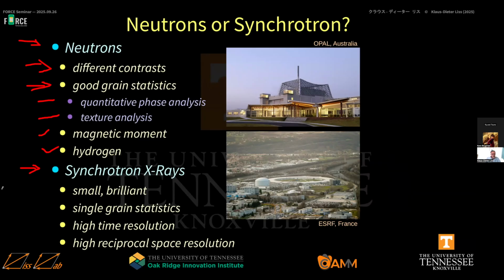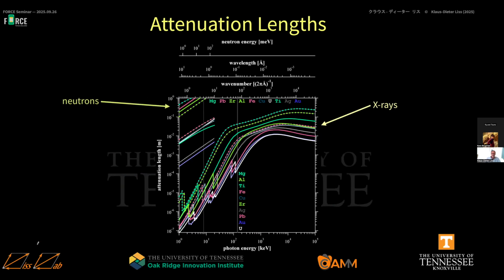Synchrotron X-rays are small, sub-millimeter, sometimes close to a micrometer squared or a few micrometers squared, and very brilliant. You have a lot of flux in these very small beam cross sections, and they're very parallel as well. That means brilliant. So we can look at the statistics of single grains with a high time resolution, because we can do fast movies. We have a lot of X-rays, and high reciprocal space resolution, because they are very bundled and come in very parallel. So the scattering angle is well defined.